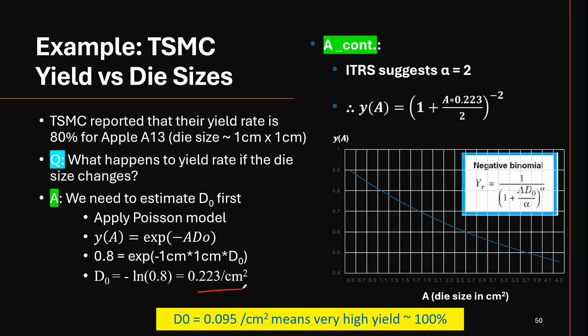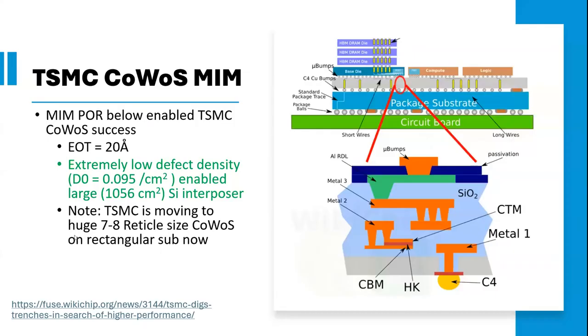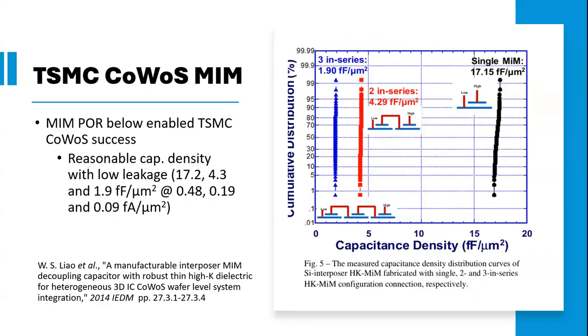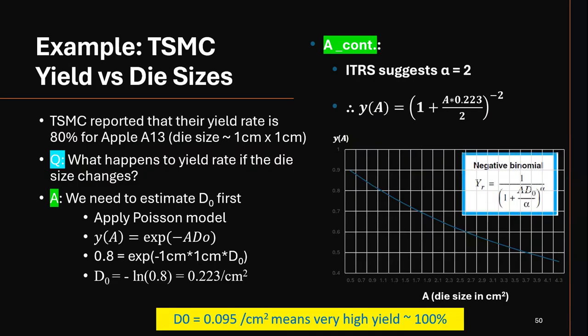It's at least 1 order of magnitude, close to 2 orders of magnitude smaller than this value. 0.2 is 80%. I would say 0.09 with a similar idea should be 95 or 99%. Oh my God, right? So 0.09 or 0.095 per centimeter squared D-naught means very high yield. I would say almost 100%. Okay.